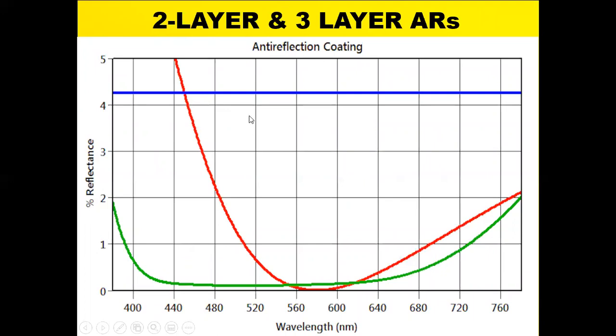Here's a few cases. The blue curve is an uncoated piece of crown glass. The red curve is a V coat of only two layers typically. The green curve is a three layer, three material coating, which has a broad anti-reflection band over the visual spectrum here. There's also a four layer equivalent of that two materials, four layers.